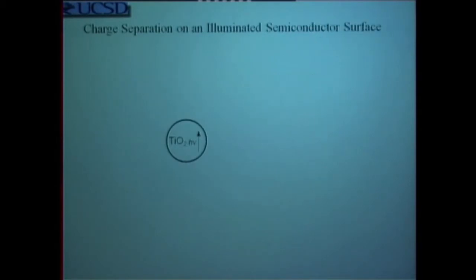So here's what happened with charge separation. Our titanium dioxide particle is exposed to light. That light has enough energy to exceed the band gap. That has the effect, in turn, of allowing that electron to be taken up by the titanium, migrating to the site which is platinized, and then to take that in a reducing equivalent to generate a reductant product.